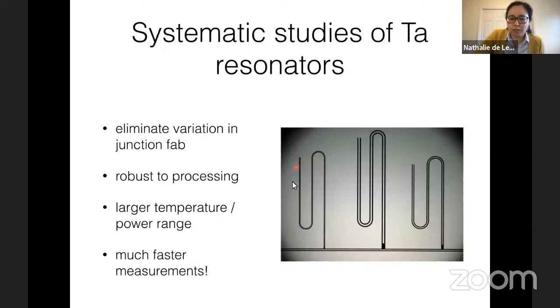So just as a first taste of some of the systematics, what we've started doing recently is try to speed up these measurements by doing very systematic studies of just quarter wave resonators made out of tantalum. So the idea is that you eliminate any variation in your junction fab, which allows you to do a much more systematic study. Tantalum is pretty robust to processing, so you don't have to worry about the fragility of aluminum. And now because we sort of get away from aluminum, we can operate over a much larger temperature and power range to try to uncover microscopic mechanisms. And importantly, these measurements can just be much, much faster.